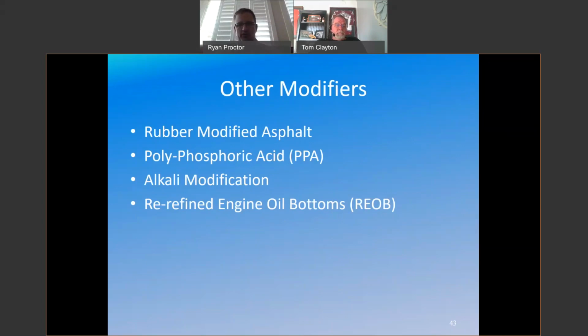Polyphosphoric acid is prohibited for use by CDOT, but there is an acid that can be used that doesn't work quite like a polymer, but it increases the asphalt's resistance to rutting. Alkali modification isn't something that I know of that people have used in decades, but that's another thing that's prohibited. And you could take a base or a caustic and do something similar to a polyphosphoric acid.